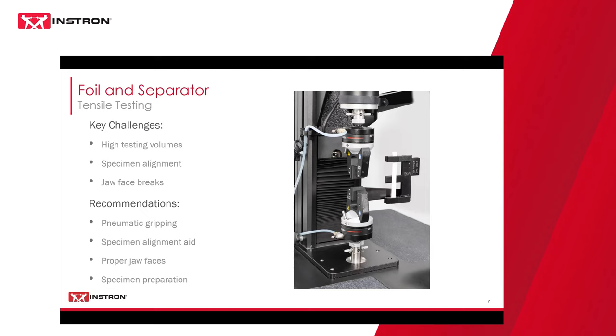Another key challenge is specimen alignment. Improper placement and alignment can lead to varying results, obviously hurting your repeatability. If a specimen needs to be adjusted in the faces, both for separator or foil, sometimes it can actually lead to a premature break when the reclamping occurs, because that same area becomes weakened by the first initial clamp. So sometimes you end up wasting material if you don't have proper alignment the first time that you try to insert a specimen.